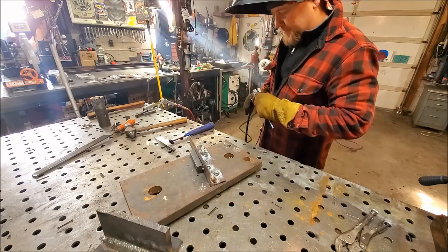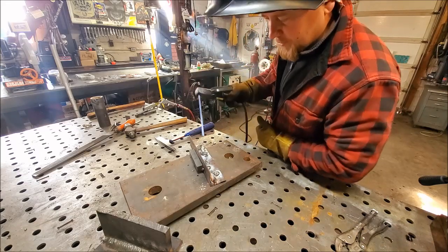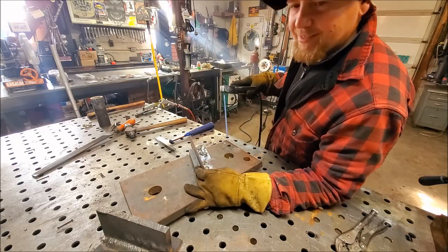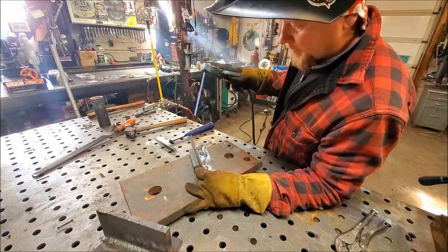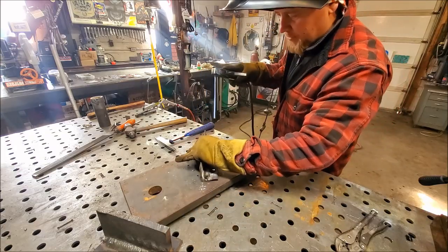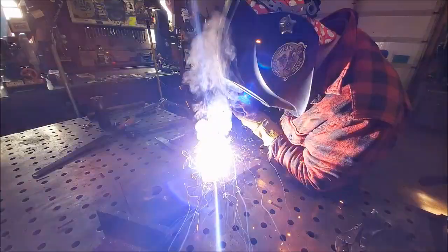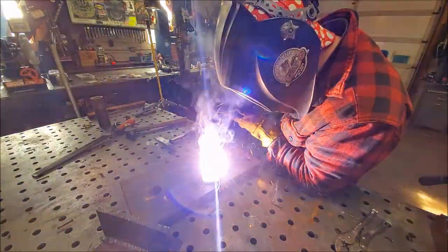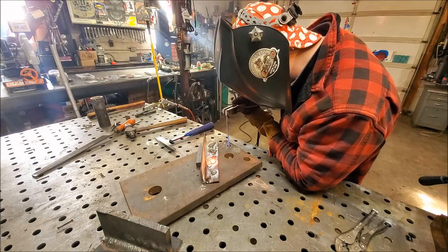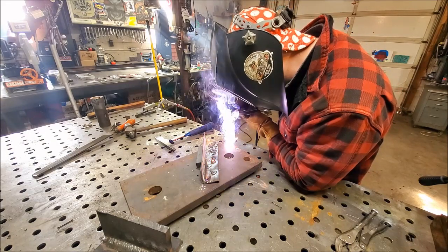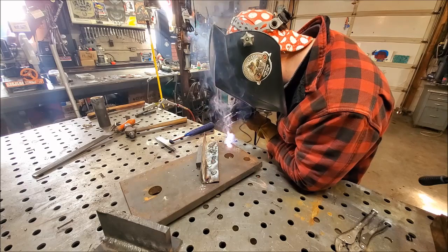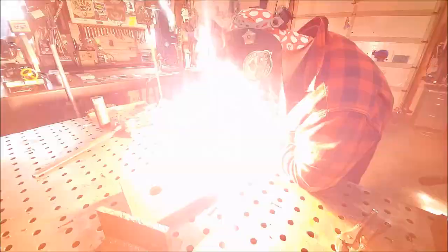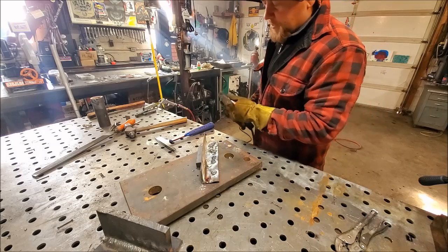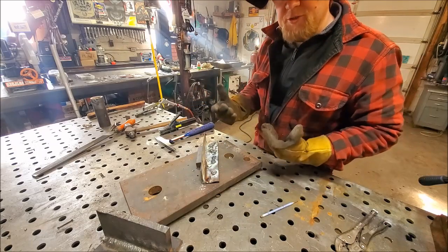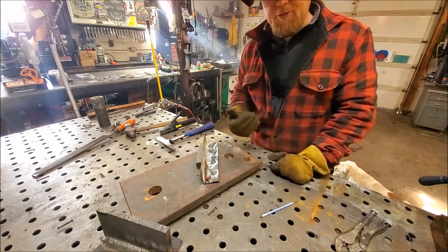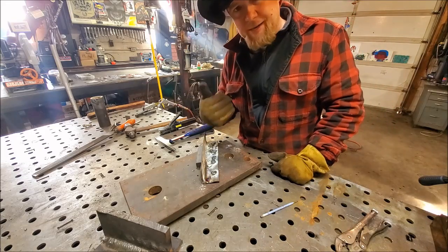So right now I'm at about 115 amps with 1/8 inch rod, 9/16 inch diameter hole, 1 inch thick. Now I'm gonna light her off, get her hot, and I'm gonna drop it right in there. I don't know if you guys can hear that or not, but the arc starts to flutter. As the arc starts to flutter, what's happening is the slag is drowning out your arc.